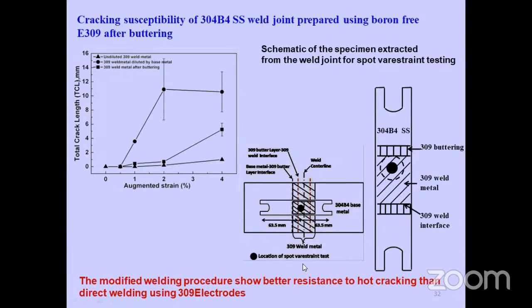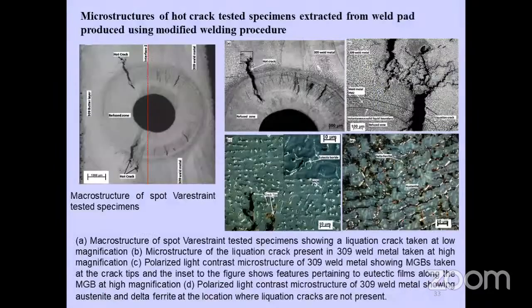So this we could demonstrate, and just by modification of this step, by adding a buttering step instead of directly joining the 304B4 base metal, we could greatly reduce the hot cracking susceptibility of the material using whatever standard available consumables we have. Without going for any borated or non-standard electrodes, we could achieve the weld joints without any cracking tendency. So here these are the microstructures taken after testing.